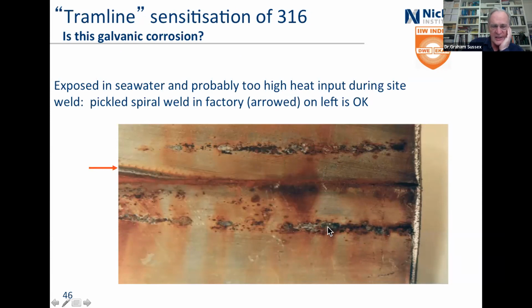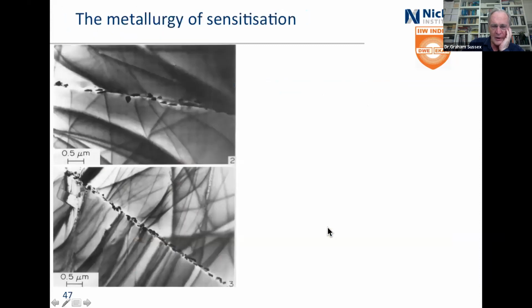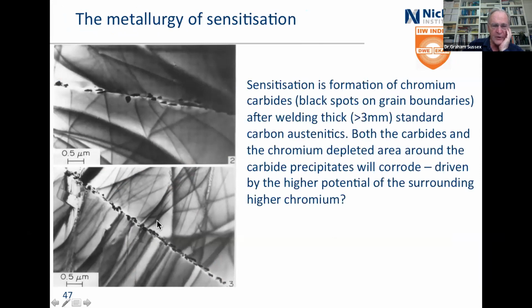Because this is an area where you get chromium carbides formed, and they form like that. If they're just scattered along like that, then they're okay, because the area around there is lower in chromium, and so it's likely to corrode. There's a differential there. And if they're contacting like that, then you wind up with carbide intergranular corrosion.